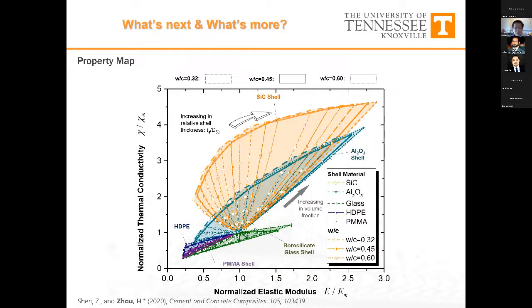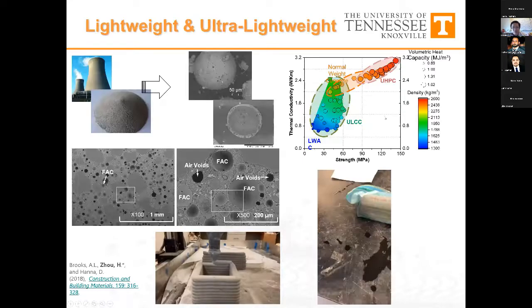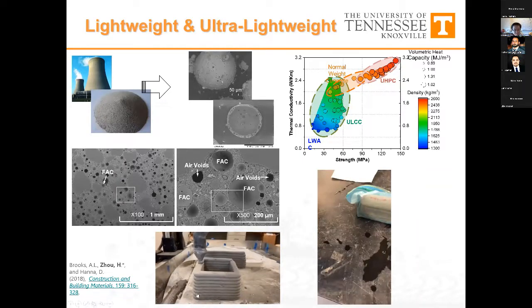So I'm going to wrap up my talk really quick with some future work, or ongoing work, that we're doing here in my group. So we took the computational model that we showed earlier, and one thing that we found out is that in cementitious systems or 3D printing in general, any soft shell functional additives that we add in, like the polymer encapsulated PCM, for example, is going to harm the mechanical property in a pretty drastic way.